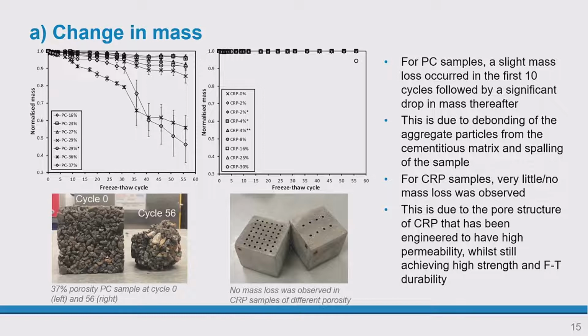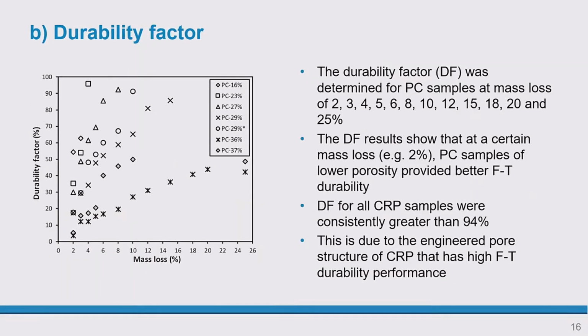And we've done some image analysis and looked at microcracking as well, and the performance didn't change when it was exposed to the different cycles. The next thing we looked at was the durability factor for both types of samples. Because for CRP the durability factor was very high, the mass loss wasn't measured at all. It was mainly more than 96%, so we didn't need to do this durability factor.